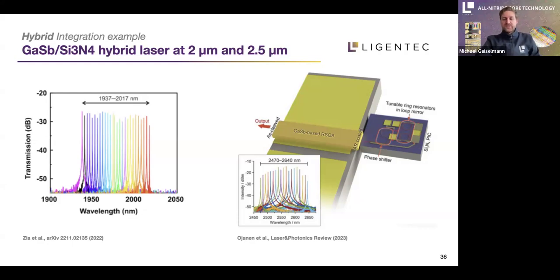You have your laser that is butt coupled to the low loss silicon nitride waveguide with integrated heaters, and you use the same physical effects to narrow the line width of your laser, and can so do that in different wavelength regions. And this is not only possible to go to higher wavelength regions, this is also possible to go to lower wavelength regions, depending on choosing a different platform of our standard platforms, 150 or 350 nanometers, whereas this work was done at 800 nanometer platform.